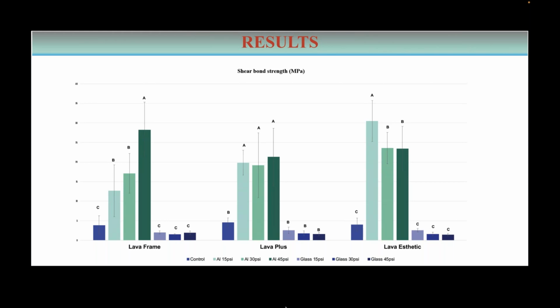For the Lava Esthetic zirconia, the A is the highest bond strength that was achieved at the 15 psi pressure, followed by the 30 psi and the 45 psi surface treated Lava Esthetic zirconia, and this difference is statistically significant. For the glass beads, it didn't produce a strength higher than the control group, and there is no statistical significance between the glass beads treated group and the control group, which received no surface treatments.